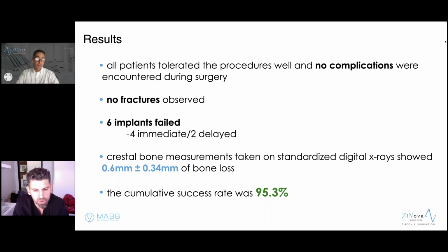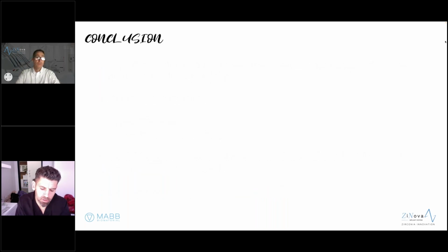So this is very comparable to what we see in the other ceramic implant studies and with our titanium implants as well, with an overall cumulative success rate of about 95%, which is a very acceptable and very good number to see with the ceramic implant. So again, we know that these implants are good for clinical use. We can treat them as titanium implants.